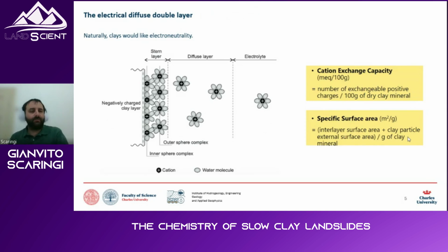So there is a partial positive and a partial negative charge, a dipole, and this dipole orients itself inside this electric field. Basically the positive part, the hydrogen, is more attracted to the surface of the clay, while the oxygen is repelled away. All these attractions form a certain structure of adsorbed water surrounding the clay.